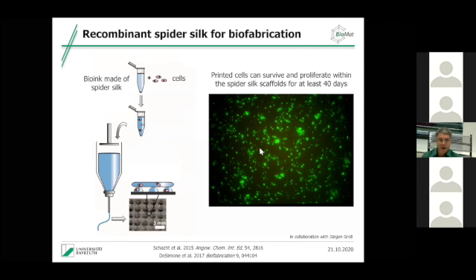And here you see a live-dead test after 40 days, and you see a lot of green dots, and probably you see no red dots. A red dot would be a dead cell. All the green dots are living cells. So we have a survival rate in the printing process of more than 99%. So actually the silk gel is not only the scaffold where the cells sit in, but it also shields the cells during the printing process. So it shields the cells from the shear stresses, from the elongational stress that appears down here at the needle. And this actually allows us now to 3D print cells with the scaffold, and they're surviving that.